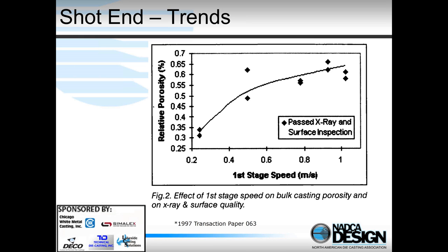But what's kind of important here is even under great control, I never got the porosity concentration down below 0.3%. So I didn't get down to 0% porosity, and to go from 0.3 to 0 from a process point of view is going to be very, very difficult.